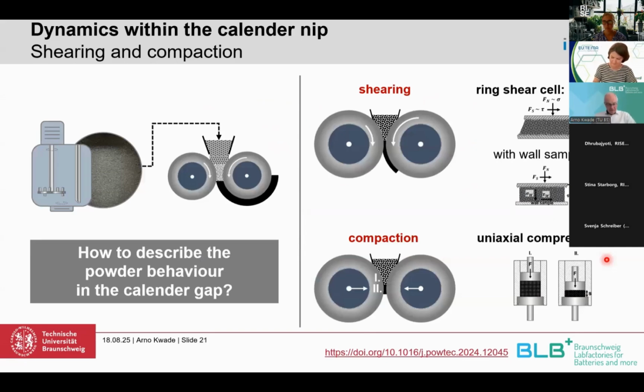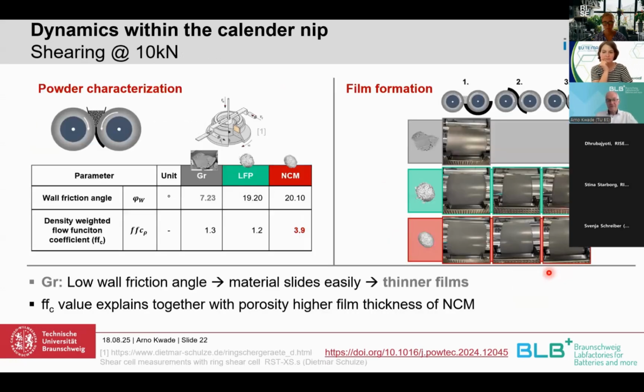Now coming to this film formation step, you see that we have normally compaction, normal stresses, but depending on the differential speed of the rollers, also some shearing. And we thought what can be a good measurement technique. So we have a ring shear cell and we have a uniaxial compression to describe that.